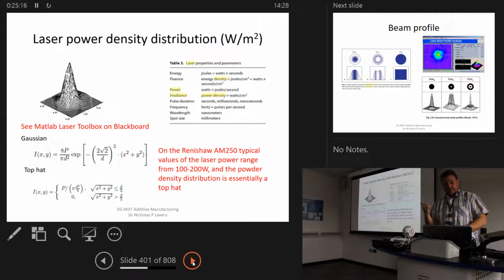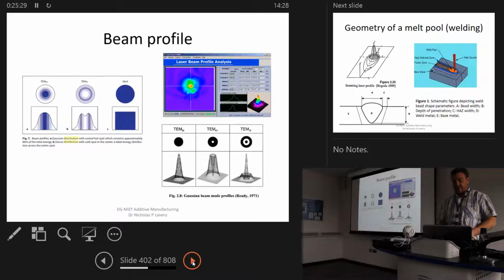distributions of the laser. The other thing that we tend to approximate a lot is the actual distribution of power through the focal area. So we'll assume that that is a top hat typically, but in actual fact we have distributions which are far from being a top hat distribution. We can have more Gaussian or double-edged ones. You can see some of these here. And you can see a real one that's coming off the beam profile analysis, which we use for calibrating. We'll typically play with the spot compensation until we've got the distribution as close to a top hat distribution as we want it.